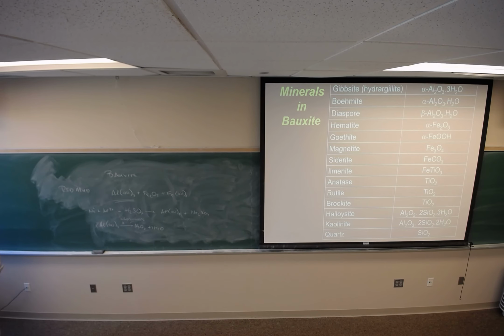Then you have halloysite and kaolinite and quartz. We don't care about quartz because we can separate quartz out pretty easily. It's also not reactive or not very reactive in the system. We care about clays though. Halloysite and kaolinite, if that's in the system, there's too much clay, you can't process the bauxite because in that digestion step you will dissolve that clay in, and then you end up with silicon in your aluminum and you can't deal with that.